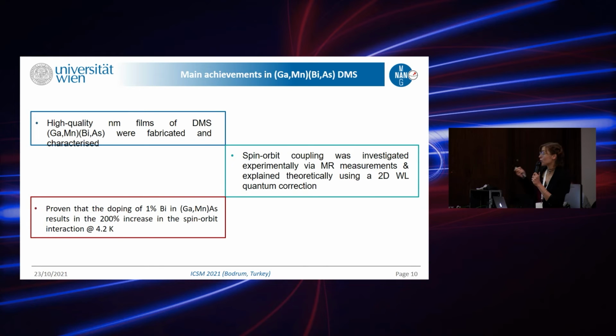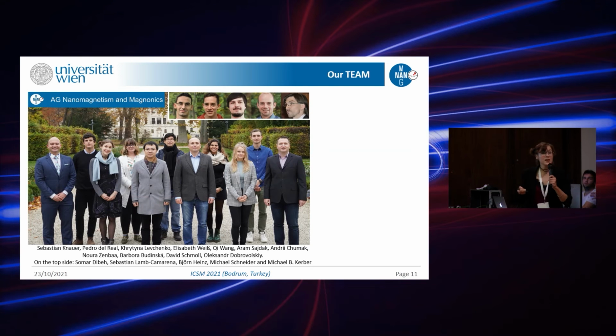This is a conclusion to the first part. We measured, I think, one of the first magnetotransport in sub 50 nanometers, in 10 nanometers thick quaternary compounds of high quality. We observe an increase of spin-orbit coupling qualitatively through magnetotransport and quantitatively through the characterization with a weak localization correction to conductivity. This was very interesting and exciting work on a spintronic material.